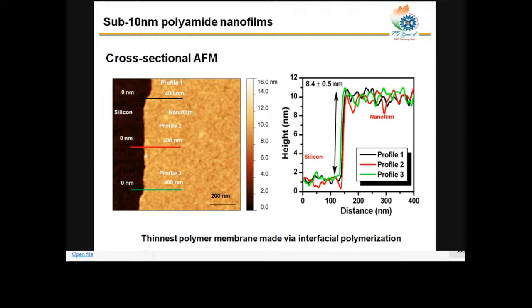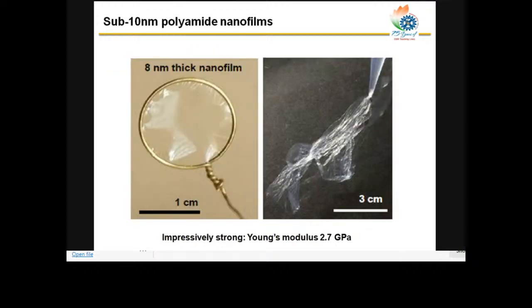So on the right side of the graph, you can see the height versus distance. If I travel from left to right, you will see the silicon wafer and a step profile, which is basically the thickness of the membrane, about 8.4 nanometer. And this one was the thinnest polymer membrane. In 2015, it was published. At that time it was the thinnest polymer membrane made by interfacial polymerization. So this sub 10 nanometer polyamide film is also impressively strong, with a Young's modulus value of 2.7 gigapascal. Although it looks very thin, it's equally strong, like 2.7 gigapascal.